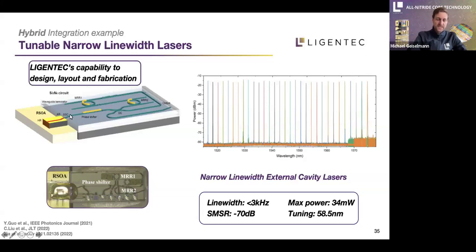Here you have a spot size converter that is adapted to the mode field of the laser. You have a phase shifter that contains a heater to change the effective refractive index of the silicon nitride waveguide, and then you have a Vernier filter with these rings that are again tunable. And here we can then in the end fabricate a chip that narrows the line width of a laser, which is usually hundreds of kilohertz, to a line width that is below 3 kilohertz in that case, and probably even sometimes reaching below kilohertz line width.